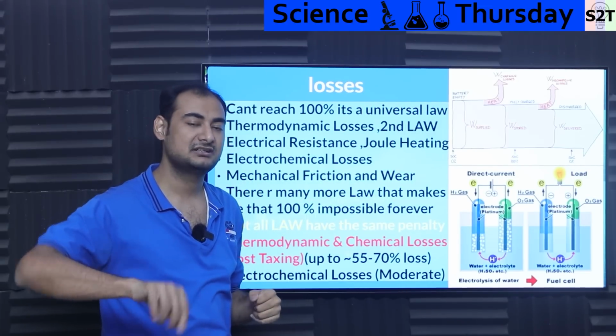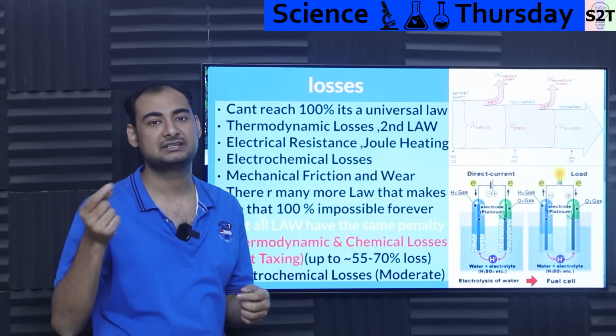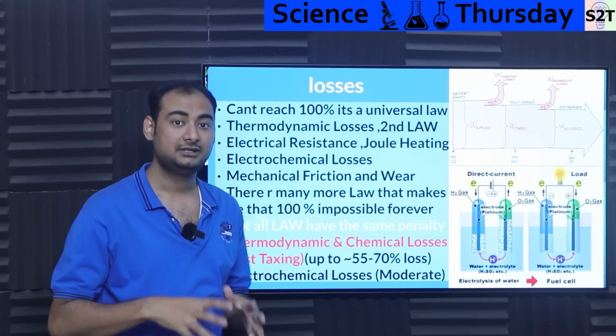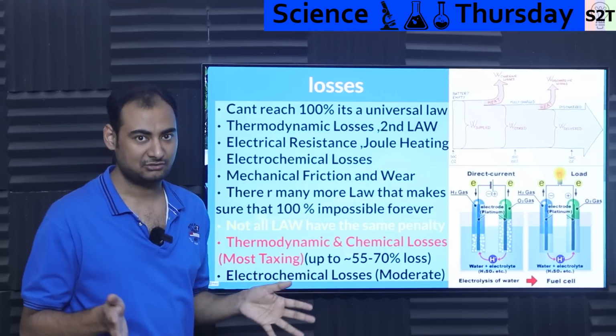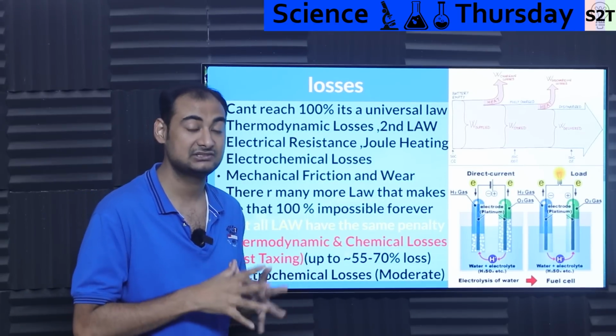It's coming from internal resistance of the cells. You must have known, like all batteries, how much oomph they can deliver is limited by internal resistance. That's there. Now again, that's why we want to do tabless geometry and all that jazz, to make sure the internal resistance is as low as possible. The heating would be as low as possible.